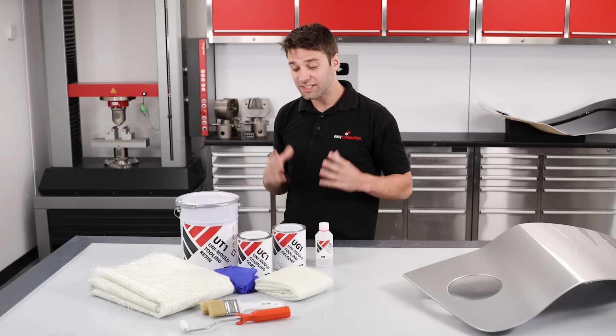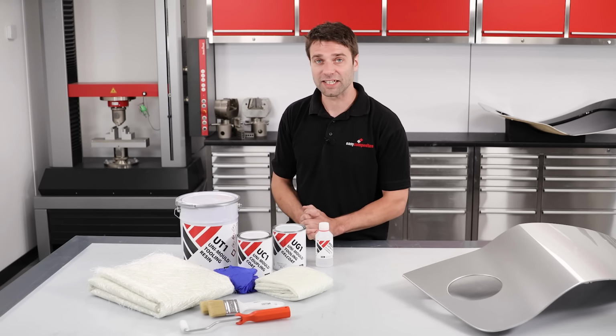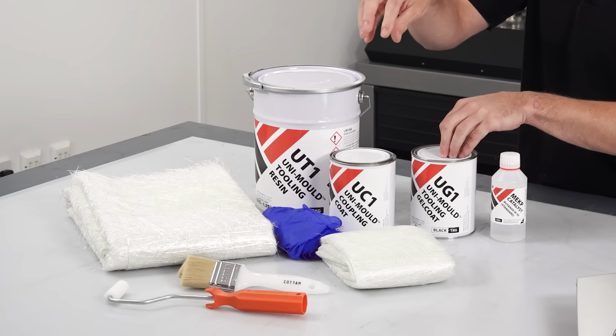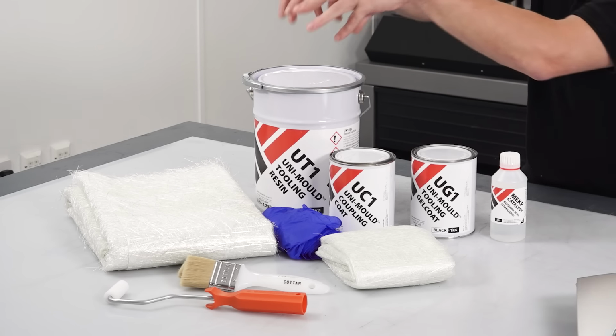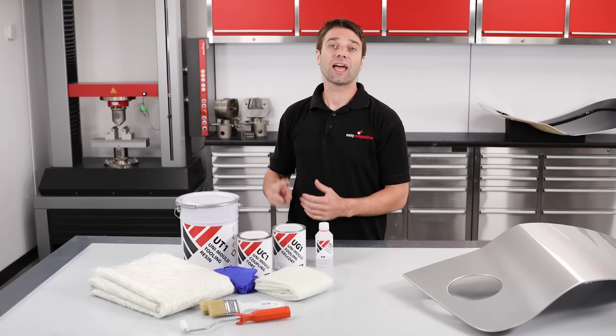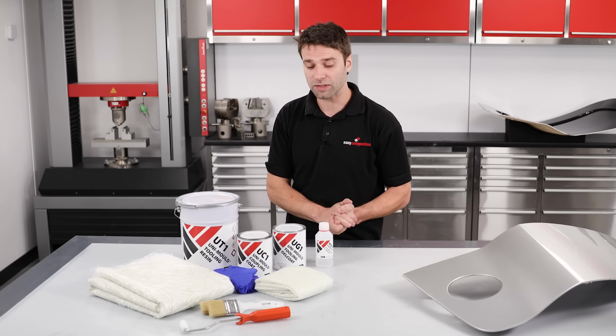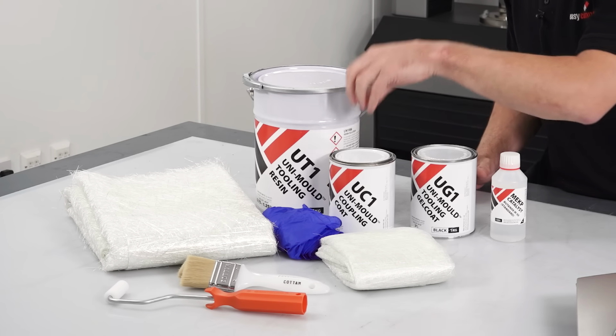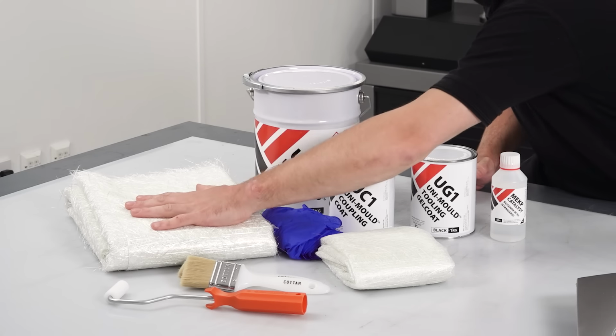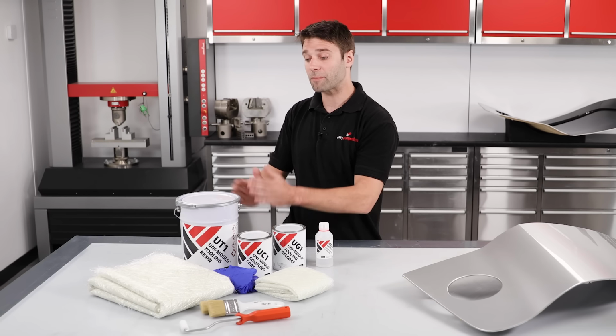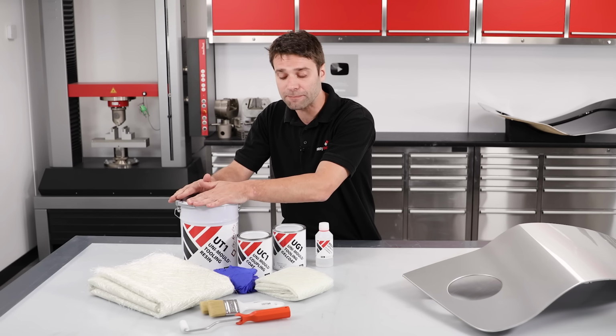The system comprises of 3 different types of resin. We have the UG1 Gelcoat, the UC1 Coupling Coat and the UT1 Tooling Resin. Then we have 2 different types of reinforcement. We use 2 plies of the lighter 100 gram chop strand mat with the coupling coat, and 4 plies of the heavier 450 gram chop strand mat is used with the tooling resin.